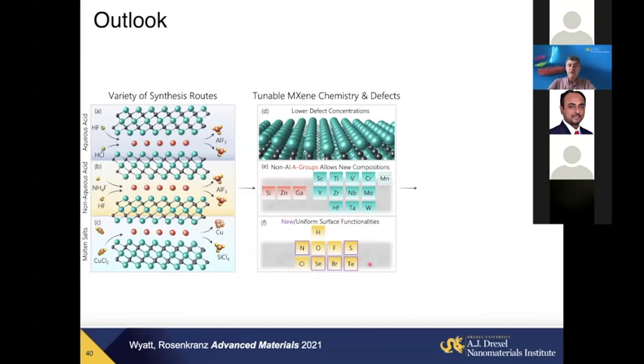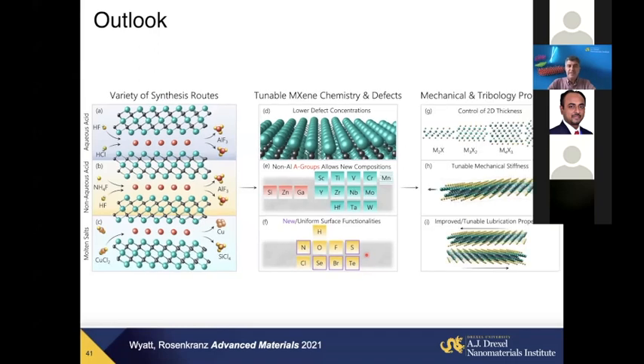But we can also explore this variety of surface terminations, surface functionalities, which further allows us to control interaction between two-dimensional sheets. So again, controlling chemistry, controlling healing or introducing defects can give further improvement in properties and also match those films to specific surfaces, to specific operation conditions here. So finally, we can also control thickness of flakes. We can control degree of delamination. We can control transition metals here, leading to tunable mechanical properties, tunable lubrication properties here.